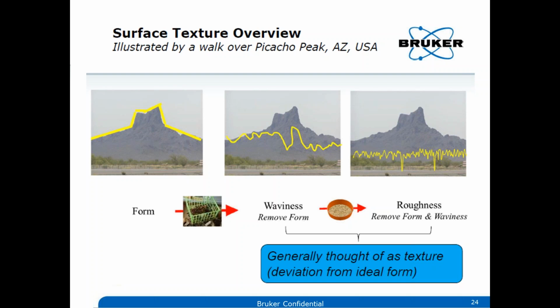So every time you make a measurement using the white light interferometry technique, you get these three data: the form, waviness, and roughness. By choosing the filter appropriately, you can get the relevant information. For example, sometimes I'm interested in the form. I'm making a ball bearing, and I'm interested in whether the radius of curvature is as per my design. Then I'm just interested in form, not waviness and roughness. In certain cases, I need the roughness data. I need to prepare a surface before I coat it with a hard coating or a different polymer coating for an application. Then I need to know the roughness so that I can estimate whether the adhesion properties will be good or not. Different applications require different parameters to be measured. Every time you measure all three, so you can get the data you want. And all three data are always stored, so you can always go back and ask different questions and get different parameters out of the software.